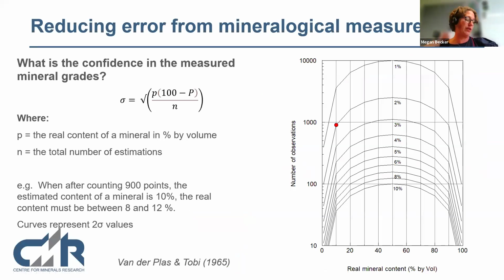Then what is the confidence in the measured mineral grades? There's this formula, it's actually a very old formula from the 1960s, and it can be used to estimate the confidence. There was a chart that went with this original paper, and if I just show you the example here, on the red dot, P is the real content of the mineral, percent by volume. In this example, we're suggesting it's 10%, and we have counted 900 points. Because it then sits on this chart on 2%, we know that for the 900 points that we've counted, the real value, this is 2 sigma, is anywhere between 8 and 12%. And some of the software actually gives you this error measurement when they report it from the actual AutoSem EDS device. So obviously, the more observations, the more confidence we have that we've estimated the mineral content correctly.